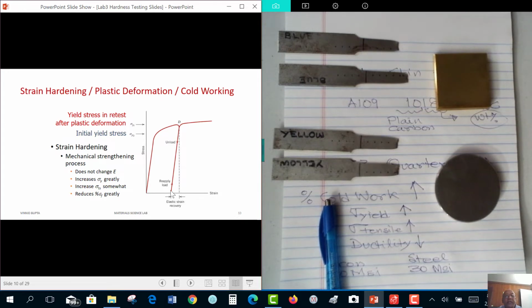So let's suppose we take the same tensile specimen and start stretching it again. So it's going to elastically deform all the way up to point D, because now that it has been strain hardened, its new yield strength is point D. And then it'll start plastically deforming again. So by giving it this much amount of permanent deformation, plastic deformation, we increased its strength. We strain hardened it. Or by cold working it by this much amount, we increase the strength. So you can see why we use these words interchangeably.